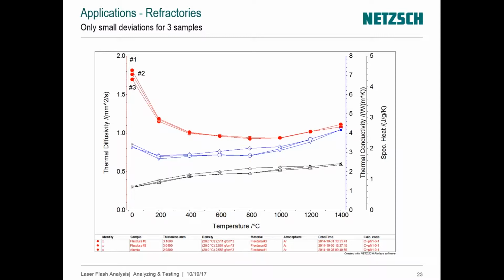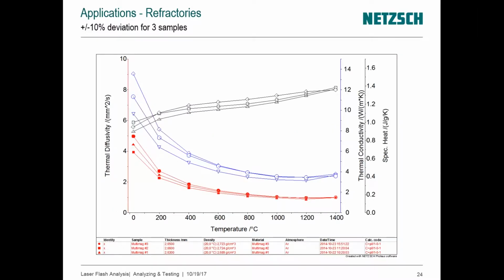The diffusivity data are depicted again in the first case. Diffusivity will decrease sharply and then reach a certain minimum and then increase again. Specific heat will tend to increase, but overall, by the time specific heat and diffusivity are combined, we do see that the thermal conductivity will increase with temperature. That was for the first type of brick. That would be for the second one. Again, the resulting conductivity tends to increase with the temperature. Very important.